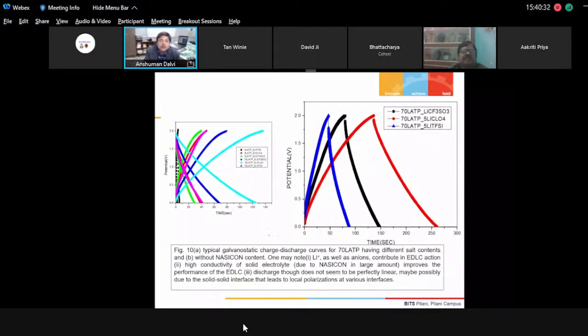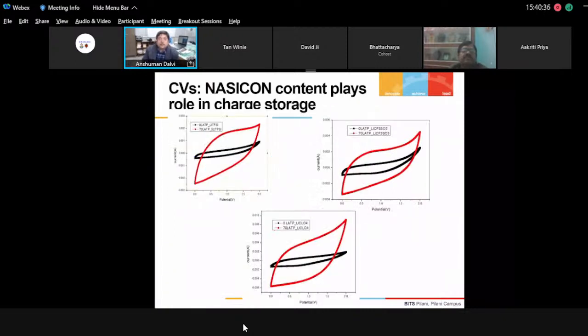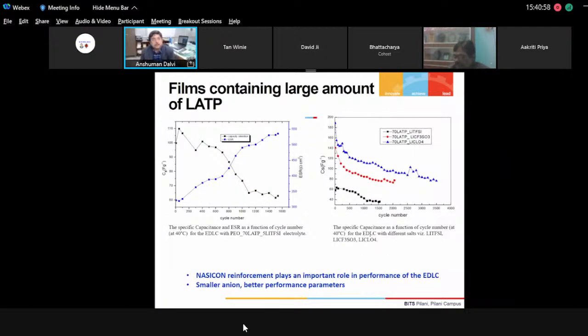And this higher capacity is sometimes even higher than some of the gel electrolytes which have been reported. So Nasicon content definitely plays a role here, and the overall conductivity of the polymer electrolyte certainly matters, and that shows that it is not necessary to have a gel, but if the interface is made smooth, then one can get very good electrical transport, and then one can get very good capacitance also. And this is indeed an interfacial phenomenon which is happening also in the solid state. So more than 100 farads per gram capacity is seen, and the ESR value we have obtained here is comparable to those of some of the gel electrolytes. Of course, it depends upon the content and composition of the gel, but many of the gel electrolytes are showing values comparable to these ones.